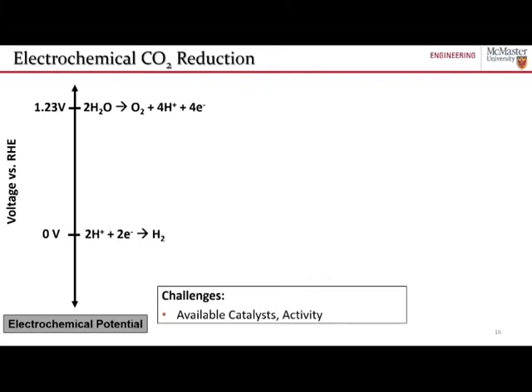The second thing is the activity of the catalysts that we do have. So I show here an electrochemical potential scale in terms of voltage versus RHE. Essentially you can look at this as the chemical potential of an electron in our catalysts or in our electrode structures. As we go lower on this plot, the chemical potential of those electrons in our catalyst material gets higher, thereby it's more thermodynamically favorable for them to react with a molecule such as carbon dioxide. We're getting more reducing as we get lower electrochemical potentials.